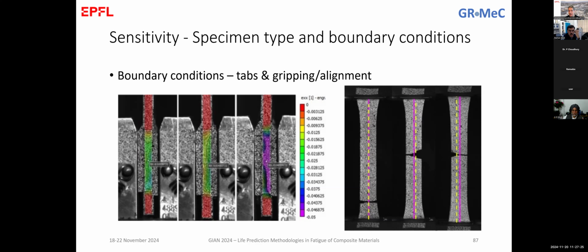And this might happen. We know this specifically for this specimen, but these are results that happen because of misalignment. Imagine you have a specimen, you put 2 tabs. If one tab is misaligned a bit because you put more glue and you didn't press well, the specimen is like that. When you close the machine, this causes stress concentrations. If there is a gap in the glue that you put between the specimen and the tab, then this again can cause stress concentrations. And this can be significant, can cause a lot of tab failures in the material.